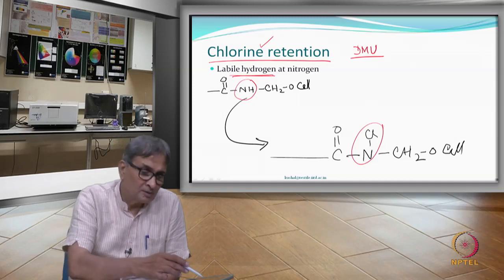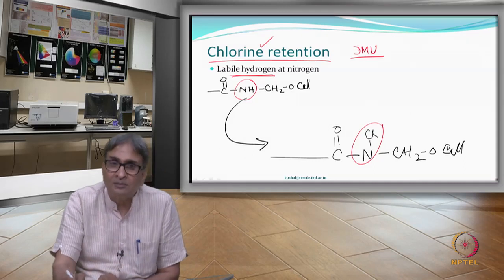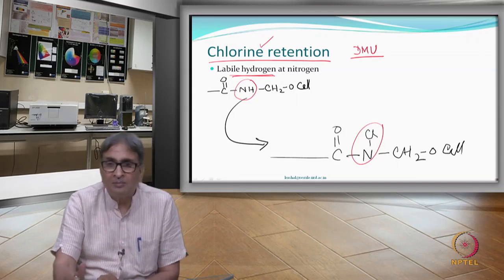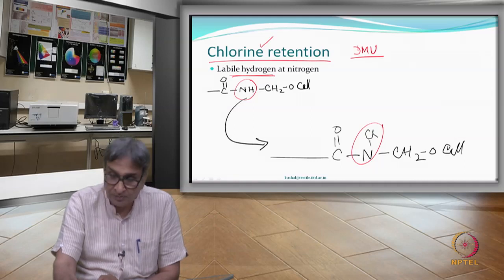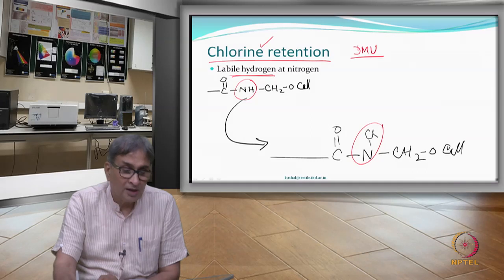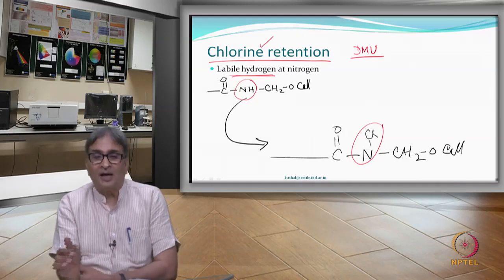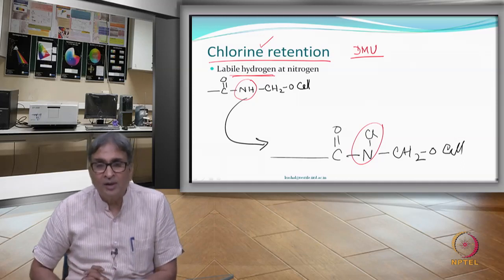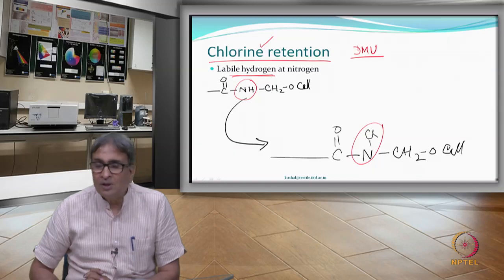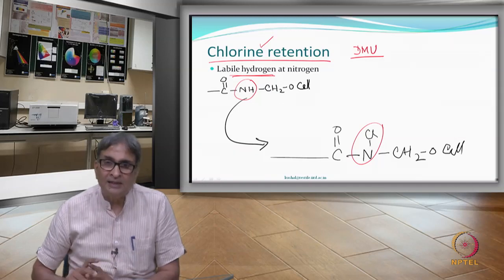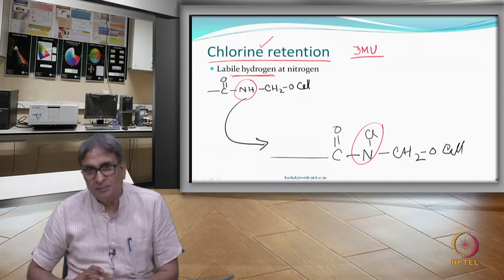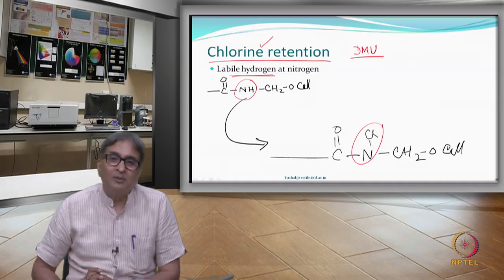That means, hydrogen on the nitrogen can be replaced by chlorine atom, because you have had some possibility of any such compounds called the hypochlorites and so on and so forth. So, you say, are we bothered about it? Yeah, we are bothered, not because of the chlorine which has been attached. If it attached chlorine, normally it is okay, but if it also can get hydrolyzed in heat and moisture, then the chlorine comes out and it can become HCl. Then HCl can be a problem.